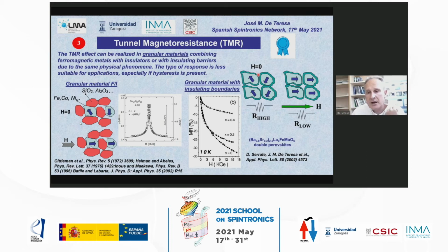A similar effect can occur in granular materials, in polycrystals, in which the boundaries of the grains are insulated. For example, we observed that in these double perovskites, these iron molybdenum double perovskites, which tend to form insulating grains, and then at zero field, the magnetization of the grains is randomly distributed, and then by application of field, you can align. And we observed at around 1 Tesla, magnetoresistance, which can be as high as 30%.